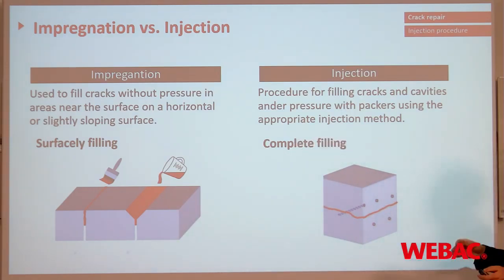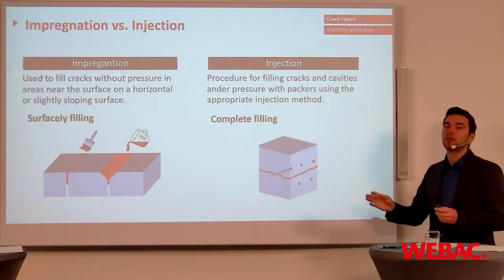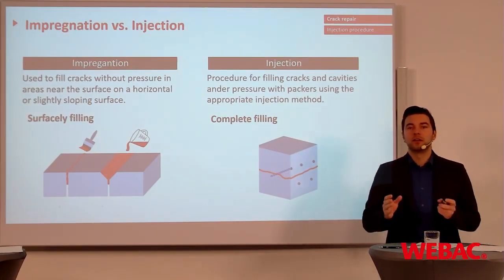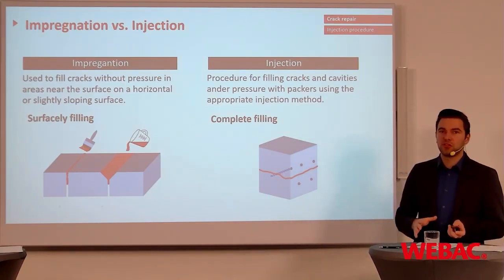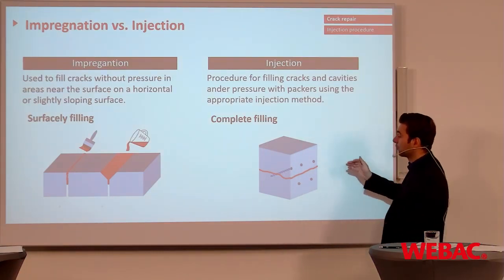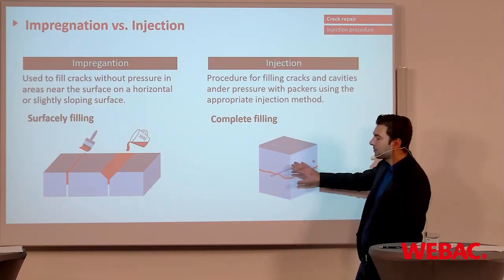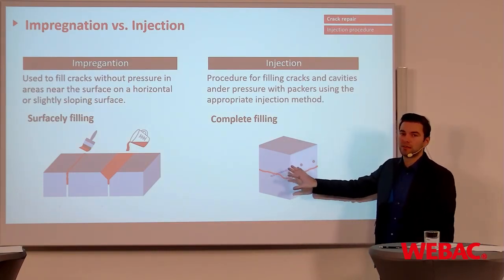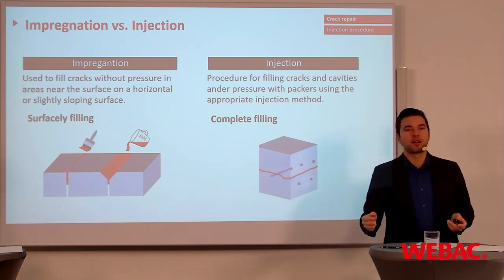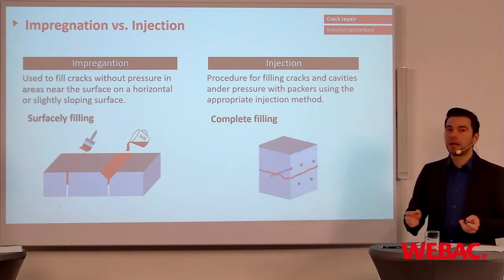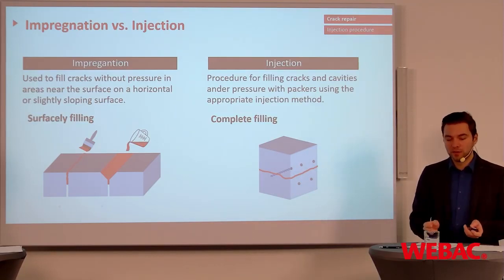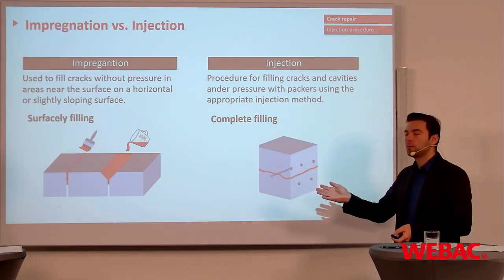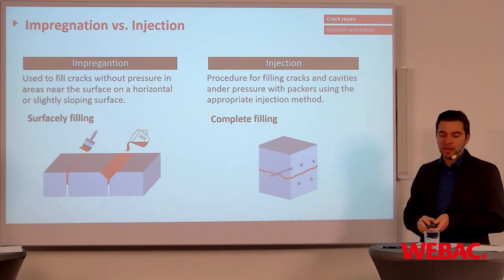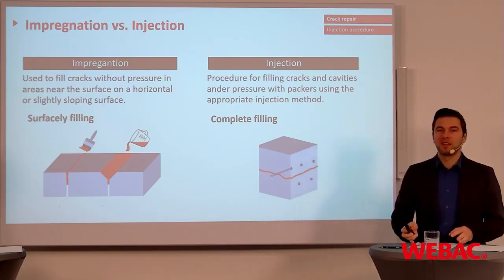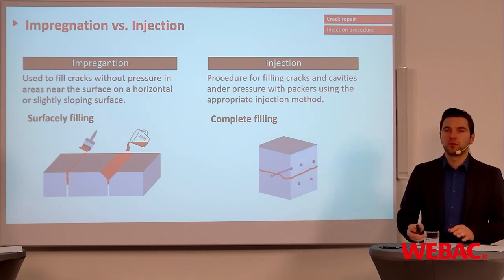In comparison to that, there is injection, meaning we are working with drilling and placing packers, using high pressure injection pumps. Therefore the filling grade inside the crack of your concrete is higher, and this is usually the target of injection: to achieve a high up to a complete filling of the crack. But in some cases impregnation might be enough, so now an application video follows which shows you the steps of impregnation.